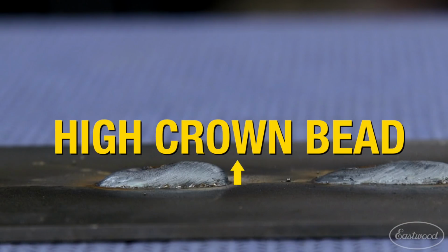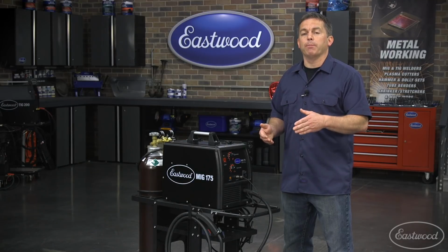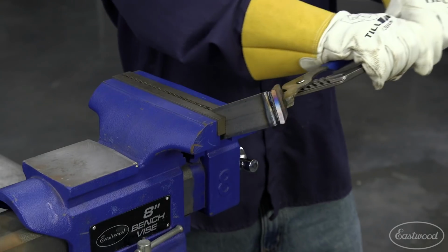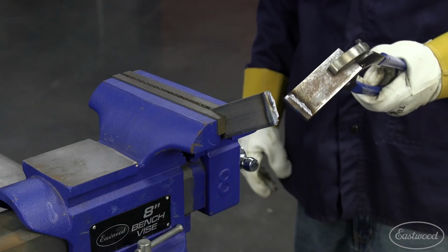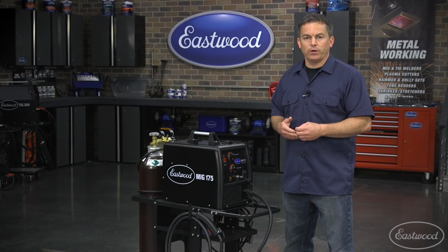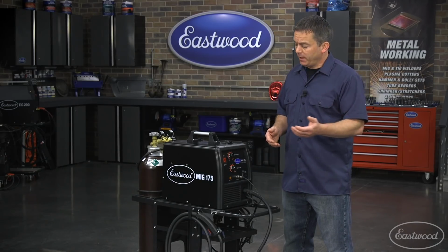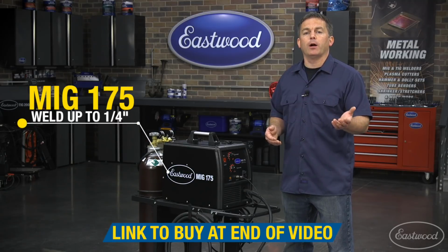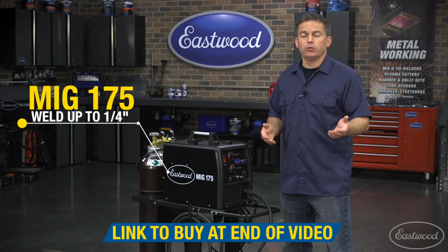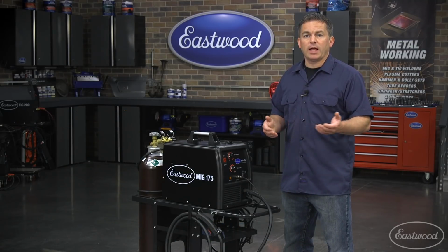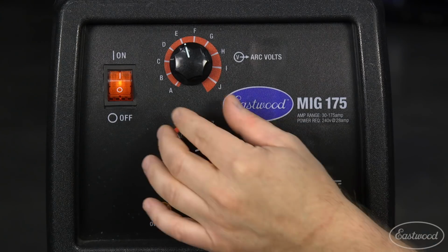These can usually be identified by a high crown weld bead, lack of discoloration from the heat on the backside of the metal, or simply because the pieces break apart easily. First, make sure the pieces you're welding aren't too thick for the machine. The Eastwood MIG 175 is rated up to 1/4 inch, so you shouldn't weld anything thicker. Lack of penetration could be caused by too low a voltage, so you can try turning up the voltage.